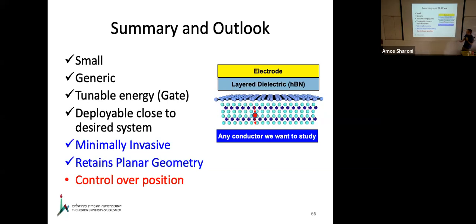Superconductors or other things. Now, another thing we discovered, this dot is minimally invasive. It means it's not a metallic dot with all its screening and everything, which is half a micron big. It's an atom, so it cannot screen on its own. And it retains a planar geometry, unlike an STM, which comes and locally disrupts the density of states and the electrical field. You have a planar geometry emanating from the fact that you have a relatively planar structure.